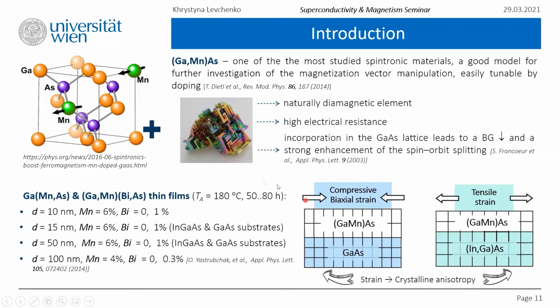Also, just a quick note: if not mentioned otherwise, the results are given for the annealed samples. Usually after the low temperature molecular beam epitaxy growth, there is some concentration of native defects, manganese interstitials. They are not built into the lattice, but sitting in interlattice positions. In order to get rid of them, you usually heat the material. In this case, it was annealed in air for a prolonged period of time. This is well known and established to improve the structural characteristics and enhance the carrier concentration.